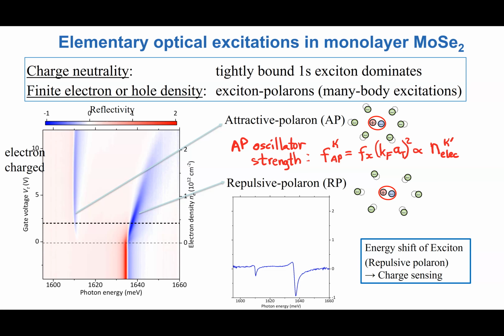And what is important is that the oscillator strength of this branch for low densities is given by the exciton oscillator strength times this quantity, which is the Fermi momentum times the size of the molecular state to the power 2. Okay? And this naturally is proportional to the electron density. But if I'm considering an exciton in K valley, it's proportional to the electron density in the other valley. Okay? And there is no bound state for electron and exciton in the same valley, and therefore there is no such resonance that occurs if they are in the same valley.